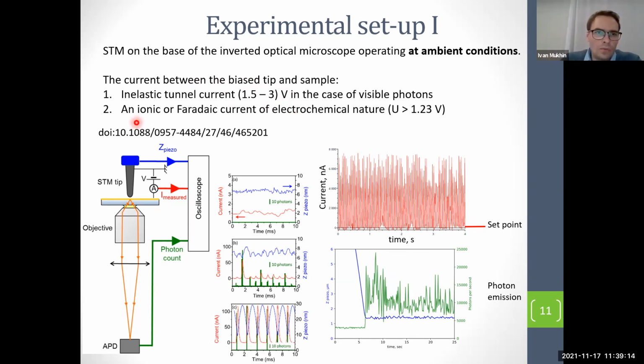As was shown in this experimental work, if you have a stable contact between the STM and the substrate, the emission is very low. If you start to oscillate, it's possible to increase it, as shown here. Here you can see the Z position. It means that the tip oscillates relative to the substrate, and you can increase light emission significantly. This is our result, this optical signal.